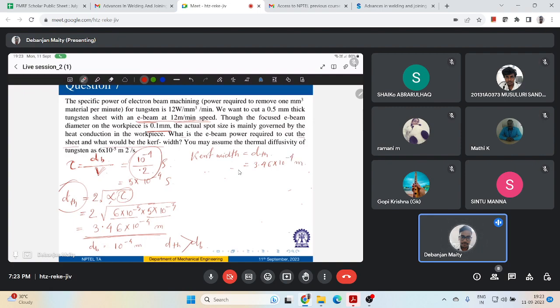Correct? Now, if I got my kerf width, that is W, and then you have your thickness, you also have your velocity, and you also have your specific power, all multiplied together will be equal to the power, is it not? So your specific power is in terms of watt per millimeter cube per minute, and you have your material removal, or if you are doing some machining, this is your material removal rate, width into thickness into velocity. Correct?